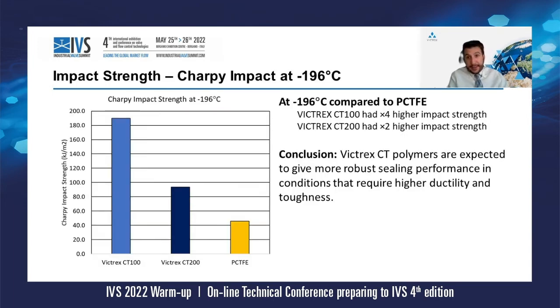As expected, both CT100 and CT200 offer higher strength while being more ductile at the same time—a combination of properties which becomes even more important if you have relatively high pressure. The impact strength is also quite important, and you can see that Victrex CT100 has a 4x higher impact strength, while CT200 has 2x. So it's a more robust seal, but at the same time more ductile. Between the two materials, CT100 is even better than CT200.